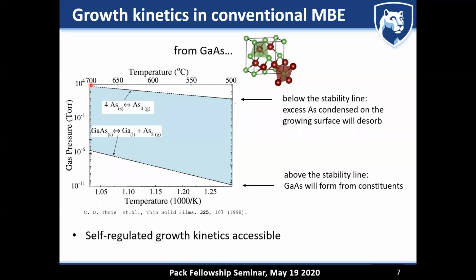And if you stay below this line, this is the stability line of arsenic, you're going to make sure that all the excess arsenic that cannot get incorporated into your gallium arsenide crystal is going to evaporate. And so this thermodynamic condition that allows for a self-regulated growth is called the growth window. And every time you have a growth window, which you typically have if one of your elements is a volatile constituent of your material, you are in game. You can always grow very high quality films by molecular beam epitaxy.